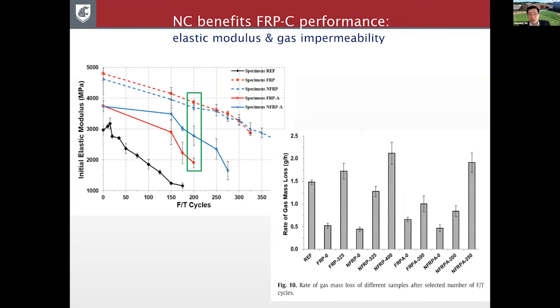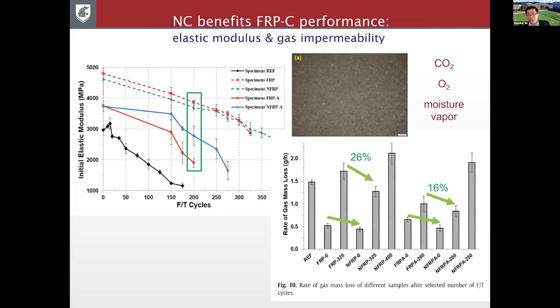And in terms of gas permeability or gas impermeability, you can see that compared with their non-modified counterpart, with nanomodification, at 0 cycles, which is prior to salt scaling, or 325 freeze-thaw cycles, or 200 freeze-thaw cycles for the pre-aged one, all of them show that the gas permeability or gas loss is less. So in other words, they preserved a little bit more gas impermeability because of the nanoclay. The benefits are about 26% or 16%, depending on whether it's a new concrete or pre-aged concrete. Again, this is due to this denser microstructure and more crack-free microstructure, keeping the CO2, oxygen, and moisture vapor outside.